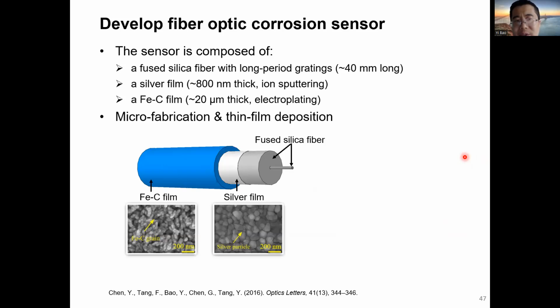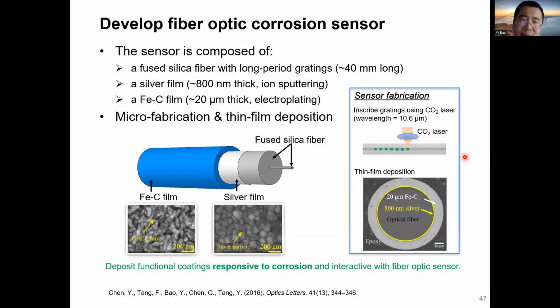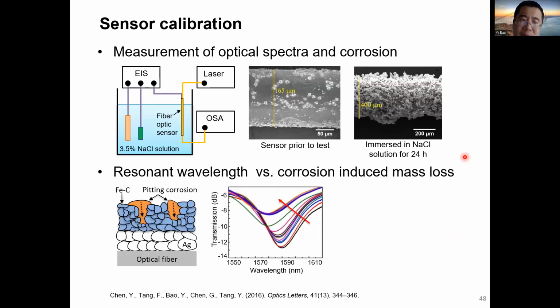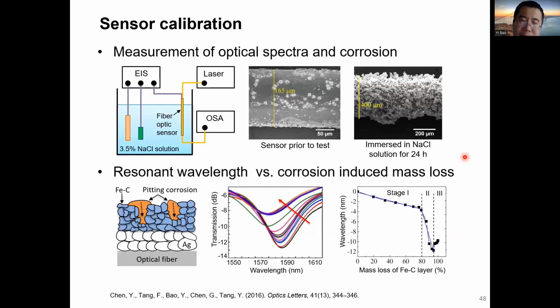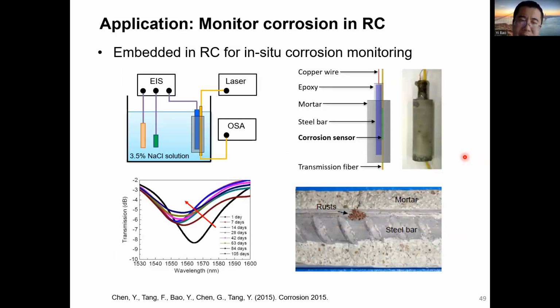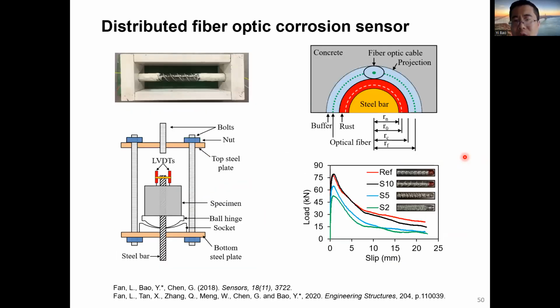Then we also did some research to develop the fiber optic corrosion sensors. Because of time, I'm not going to elaborate those work. But based on those research, we found that the fiber optic sensors could be applied to monitor steel corrosion, and we developed the empirical data, empirical formula, and some theoretical models to relate the fiber optic sensor data to the corrosion severity.